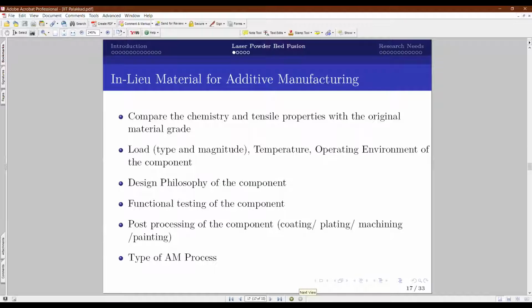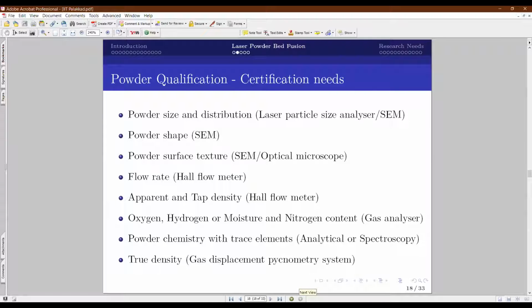Of course, what is the type of AM process? Currently we use only laser powder bed fusion, but looking at the long term, in future electron beam based or direct energy deposition based processes will also come into the picture. These are the factors we look at before freezing the equivalent material in 3D printing for a particular aerospace component. Next, let's say I have frozen the 3D printing grade, like titanium 6 aluminum 4 vanadium.